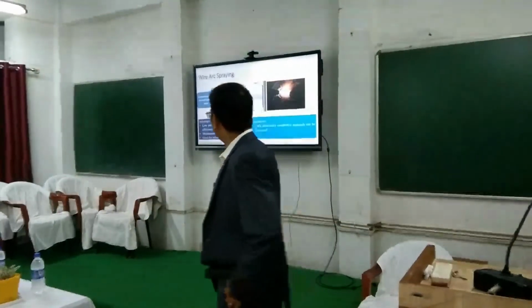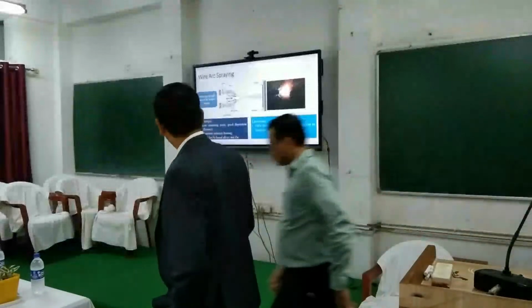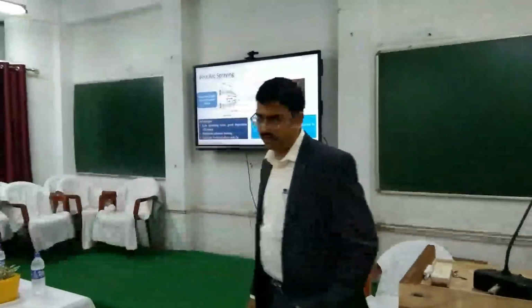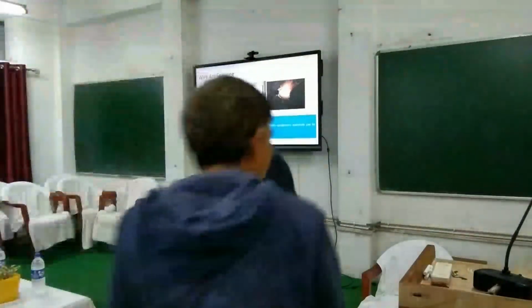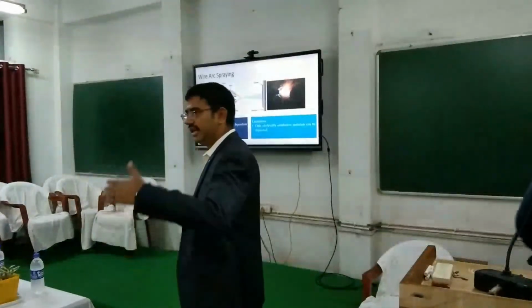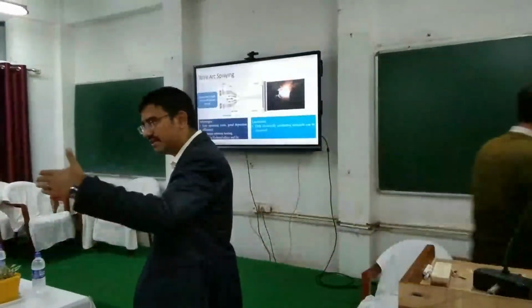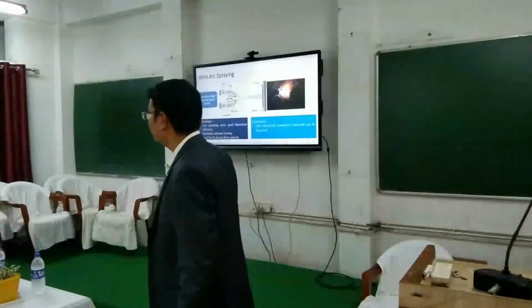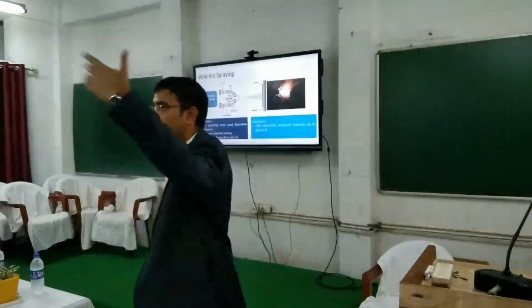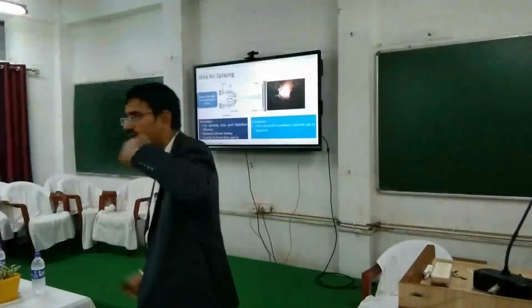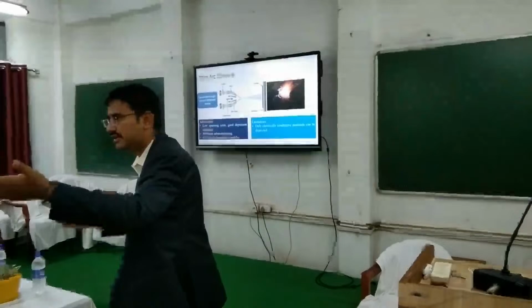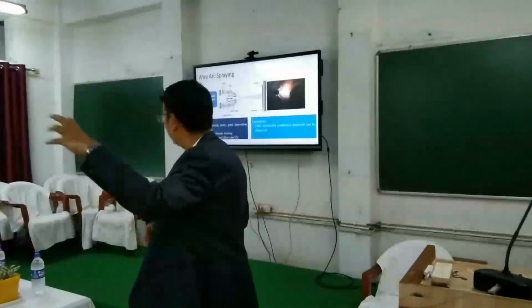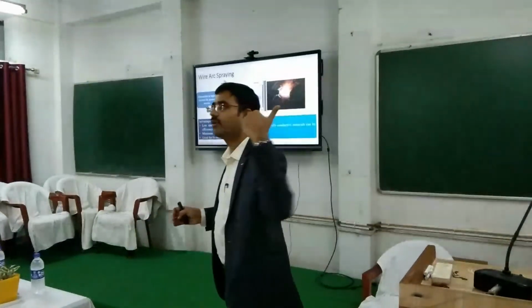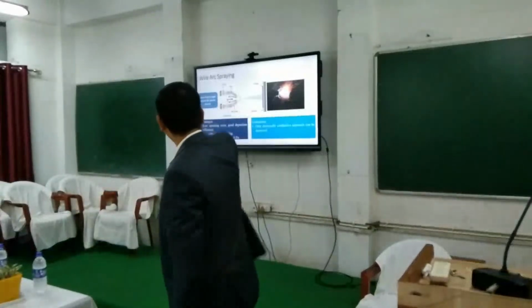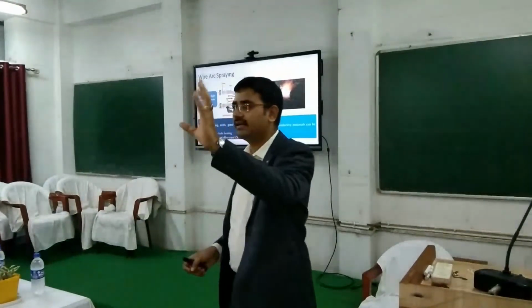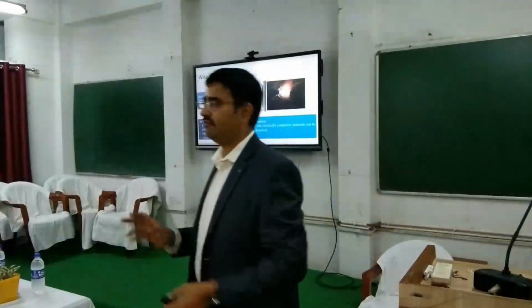So people also use wire arc spray. In that, there are some materials where making powders is not very feasible. So there they make them as wires and rods if available, and connect them to a DC power source, one given positive polarity and one negative polarity, and they are touched and an arc is generated. Within the arc the wire melts, and a propellant gas given from the bottom accelerates it, and it hits and forms a coating.